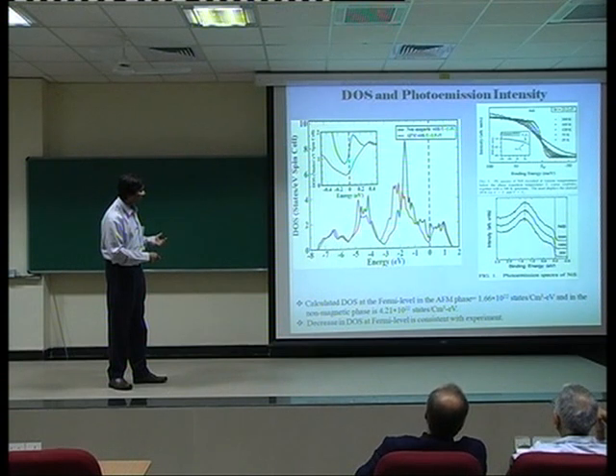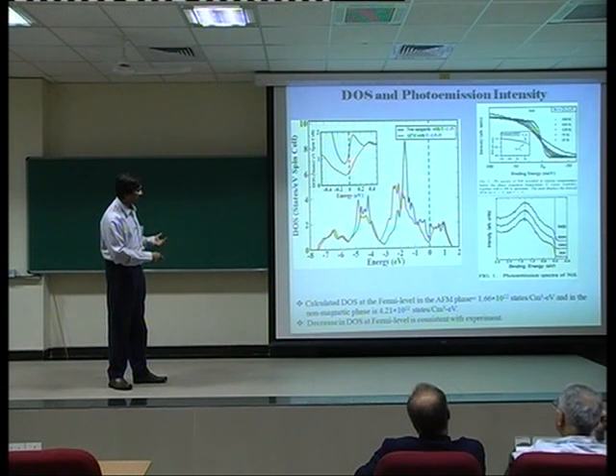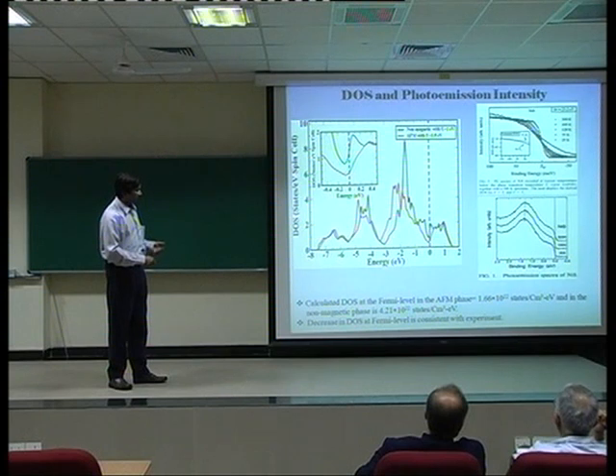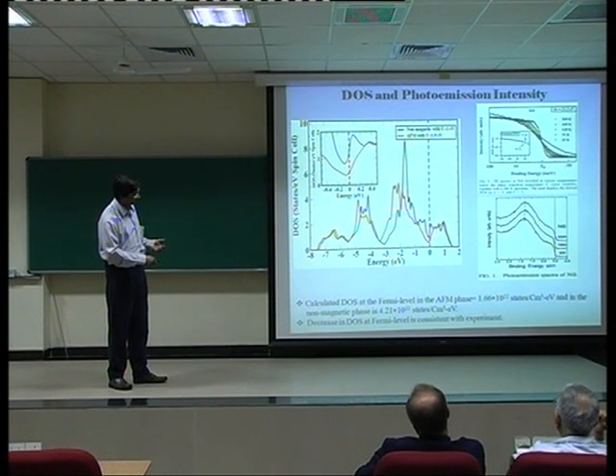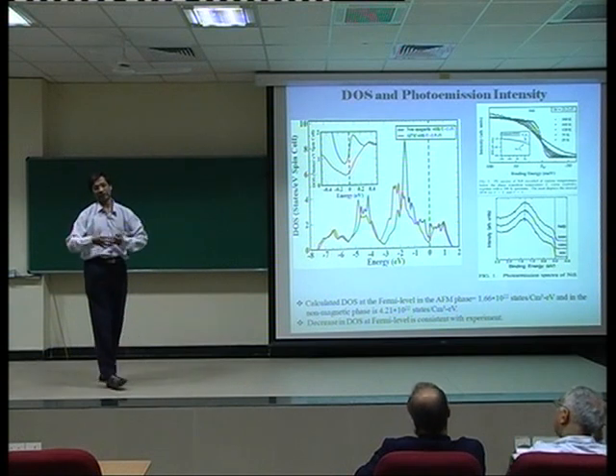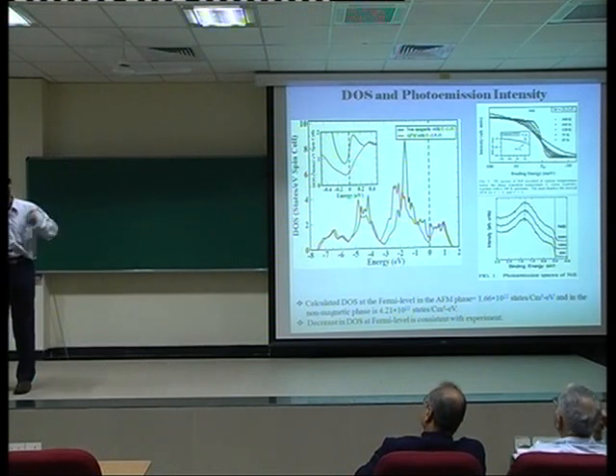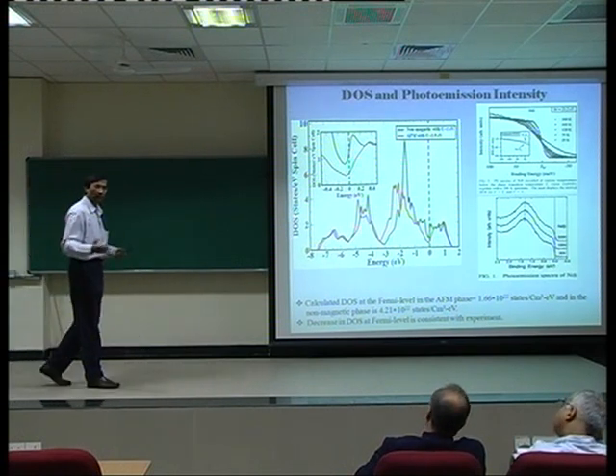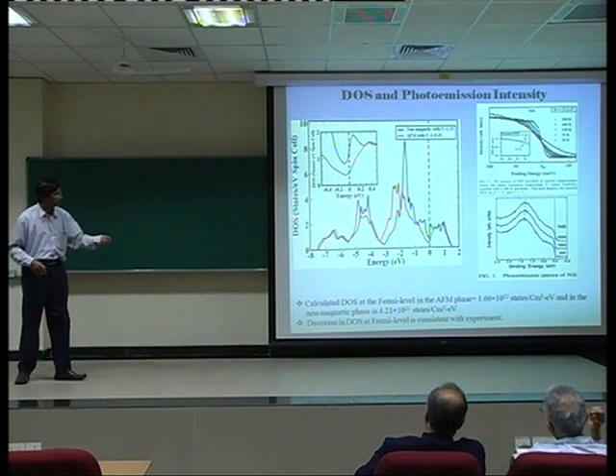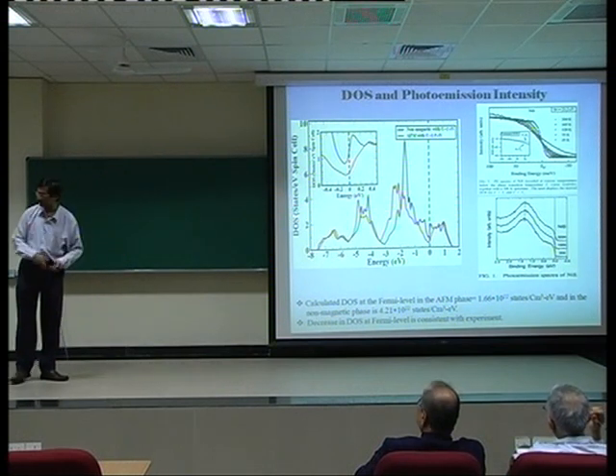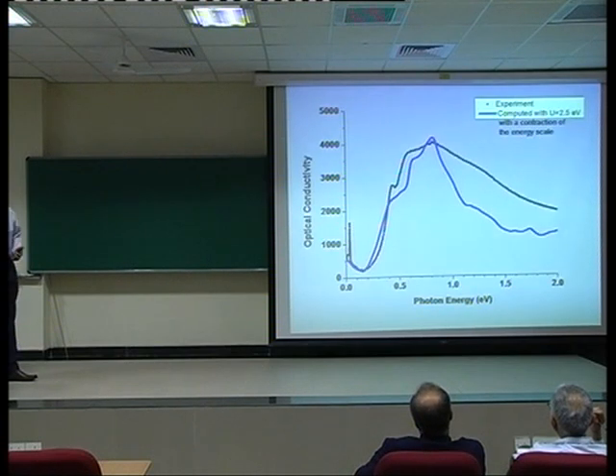And what we essentially see is that the main peak in the spectrum will shift from high binding energy to lower binding energy, exactly as was seen by Fujimori. There's continuous density of states right across. It's always metal, but there's a depletion of density of states because in the antiferromagnetic metallic state, parts of the Fermi surface drop out, but other parts still remain, and that's why you have a lowering of the intensity. And then we go and look at the optical data.